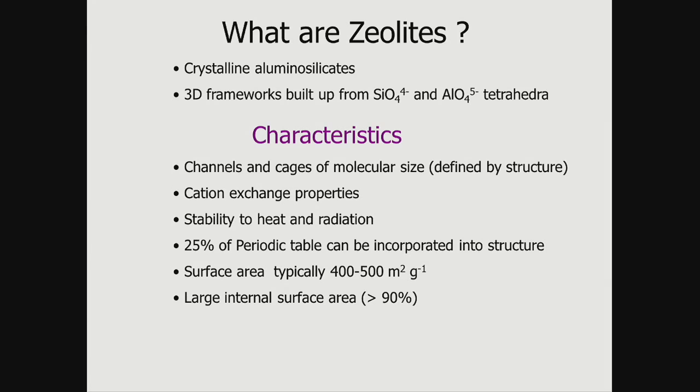So that adds to another thing. Zeolites themselves have a unique structure. They're very thermally stable. So people like me make new structures all the time, and we say, we've invented this great structure. My problem is I'm too much like you lot than I am like my brothers and sisters in chemistry. So where these beautiful structures are lovely, and it's taken a lot of science, they're not worth a damn because they can't go above a temperature of about 120 degrees C, so they're no use for anything in catalysis, so they're no use for oil and gas. Zeolites will go up to, quite happily, 600, 700, 800 degrees C, and they're still stable.